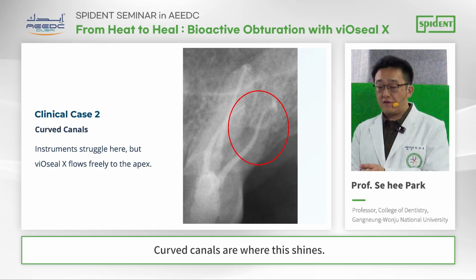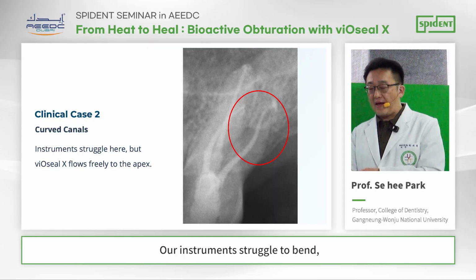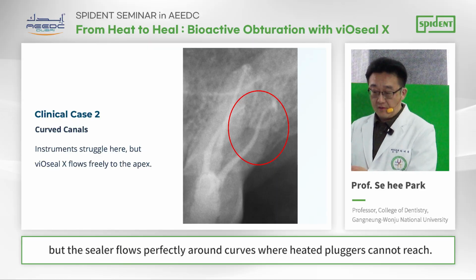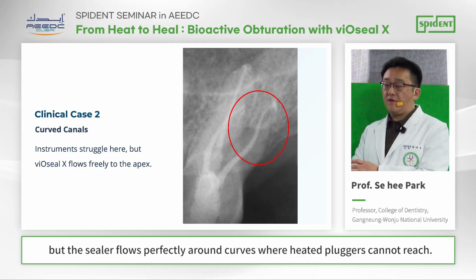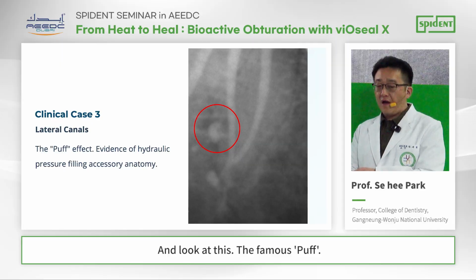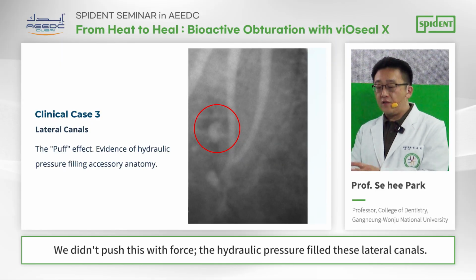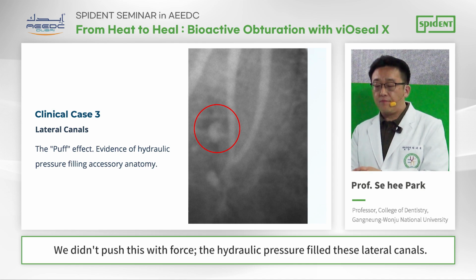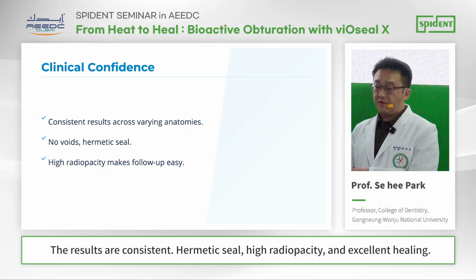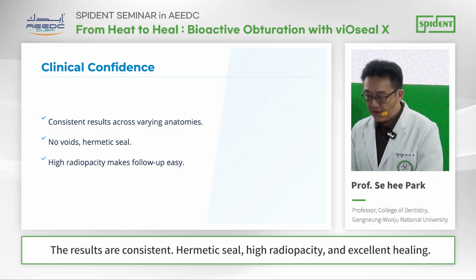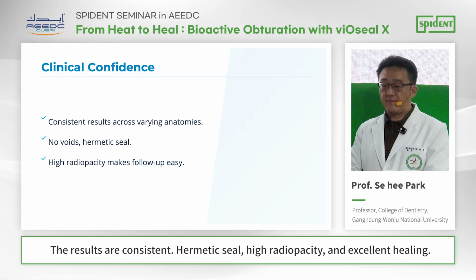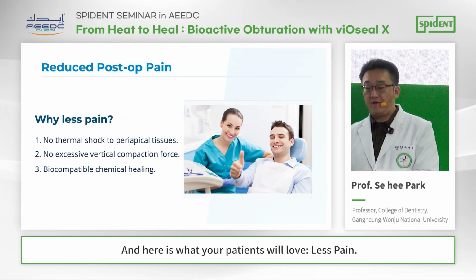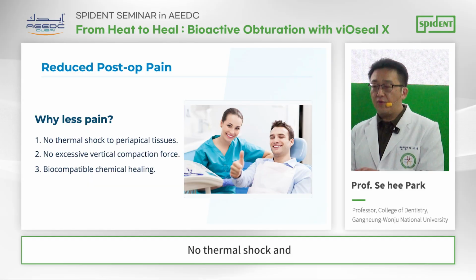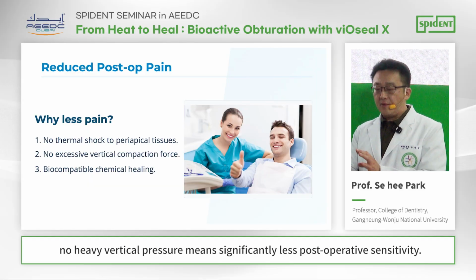Curved canals are where this shines. Our instrument struggled to bend, but the sealer flows perfectly around the curves where a heat plugger cannot reach. And look at this, the famous puff. We didn't push this with force. The hydraulic pressure filled these lateral canals. The results are consistent. Hermetic seal, high radiopacity, and excellent healing. And here is what your patients will love. Less pain. No thermal shock and no heavy vertical pressure means significantly less post-operative sensitivity.